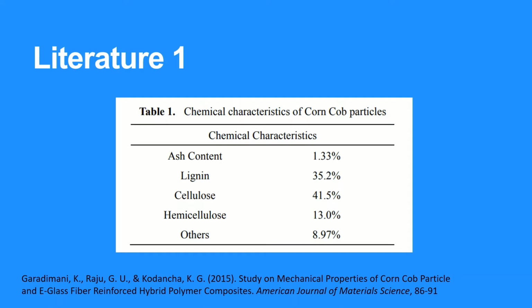Corn cob is a lignocellulosic material. In the study of Garodimani et al., 2015, they fabricated hybrid polymer composites reinforced with corn cob particles and e-glass fibers. In their research, they determined the chemical composition of corn cob particles. According to them, corn cob particles are composed of ash content, which is 1.33%, lignin, that is 35.2%, cellulose, that is 41.5%, hemicellulose, that is 13%, and others, which is 8.97%. They also concluded that the aforementioned hybrid composite can be an alternative to composite materials reinforced with synthetic fibers.